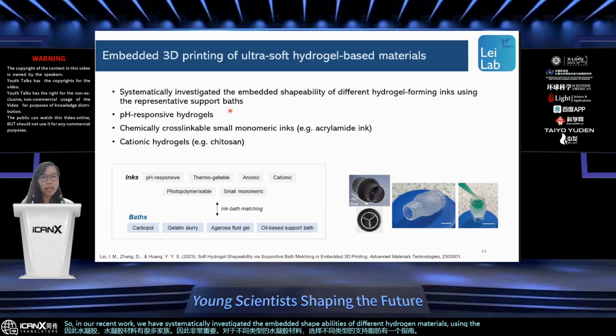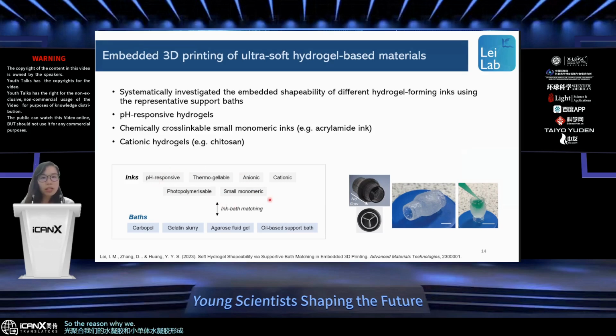representative supportive baths in literature. The inks we tested here are pH-responsive hydrogels, thermal-responsive hydrogels, anionic hydrogels, cationic hydrogels, photopolymerizable hydrogels, and small monomeric hydrogel-forming inks. The reason why we chose these inks for testing is because these materials mostly cover the materials utilized in biomedical research and soft robotics research.